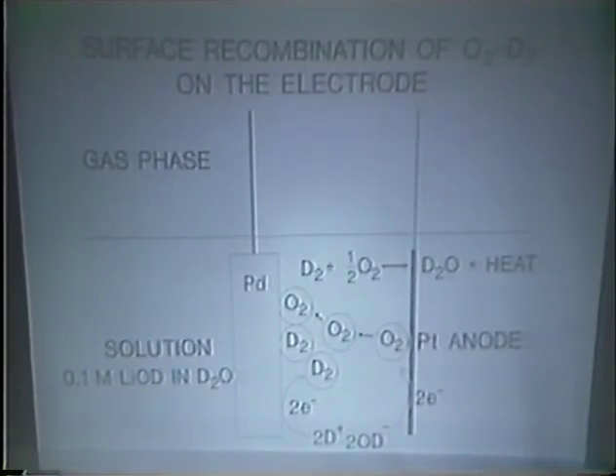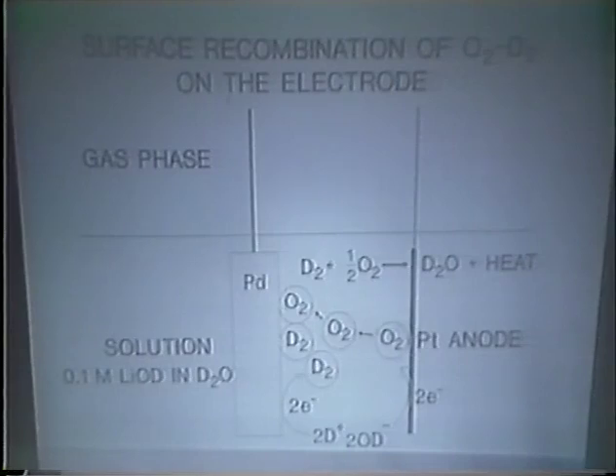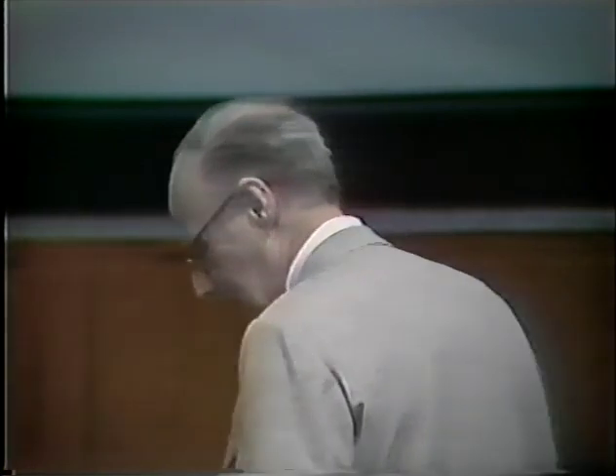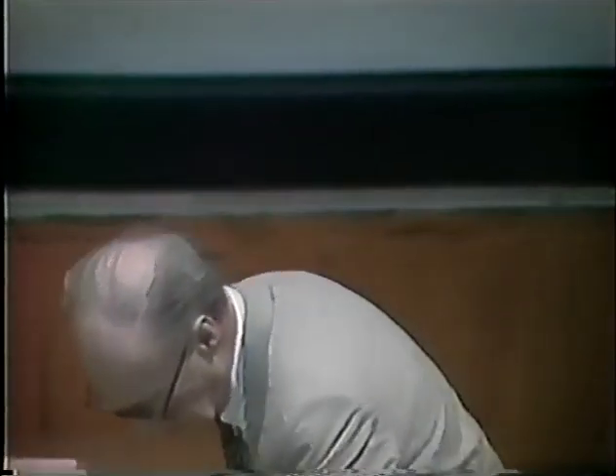the cathode and anode are pretty near together, and there's very, very vigorous evolution at 1 amp per square centimeter, perhaps the bubbles momentarily touch the electrode and give a direct palladium-oxygen contact. And there being zillions and zillions and zillions of bubbles, even if the contact lasts for a nanosecond, perhaps it would give something. And that's indeed a tenable hypothesis.